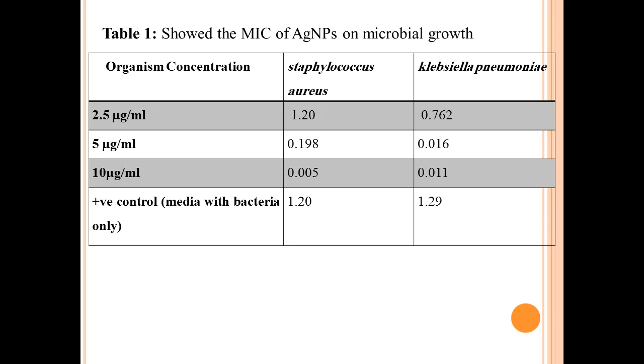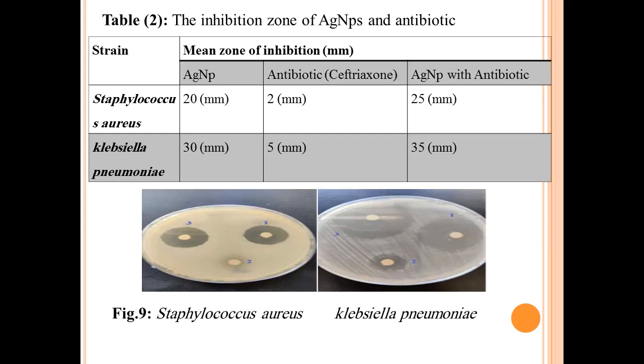Table 1 shows the MIC of silver nanoparticles on microbial growth, Staphylococcus aureus and Klebsiella pneumoniae. The concentration giving total inhibition of the bacteria is 10 micrograms per ml. Table 2, the inhibition zone of silver nanoparticles and the antibiotic on Staphylococcus aureus and Klebsiella pneumoniae. The inhibition zone of silver is larger than that of the antibiotic, so the inhibition zone is the largest when we make mixtures of silver nanoparticles with an antibiotic.